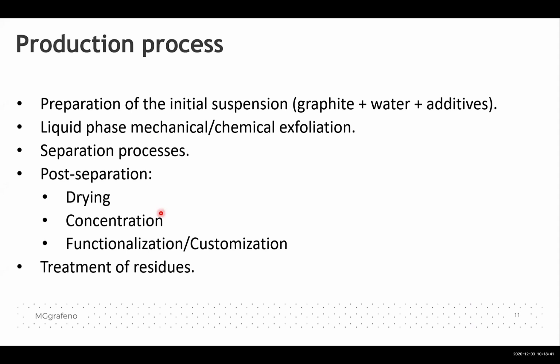Right now, we can take a suspension of graphene and concentrate it up to 3 times. So we start with like 0.6 grams per liter, and we end in the suspension with 2 grams per liter of high quality graphene. And we also are doing this functionalization, customization, and of course, the treatment of residues. Okay, and we do that with the graphite supplier, that is the Nacional de Grafite Company.